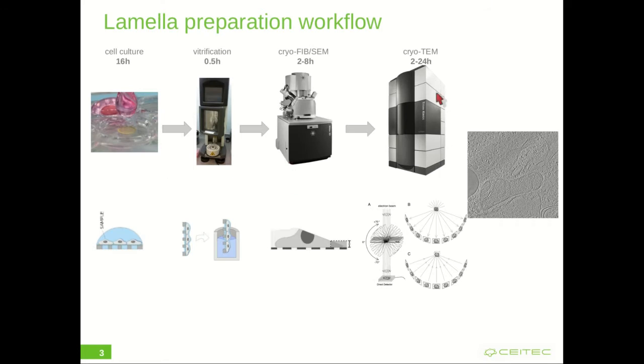Here is an overview of the Cryo-FIB-based workflow for preparation of the specimen for in situ structural studies at high resolution. As you can see, the whole workflow is still very complex and time-consuming, comprises utilization of several high-end instrumentations and transfer in between them, which increases the risk of sample damage and decreases the throughput of the whole workflow. We have tried to address individual steps in the workflow to increase the throughput and the reproducibility.